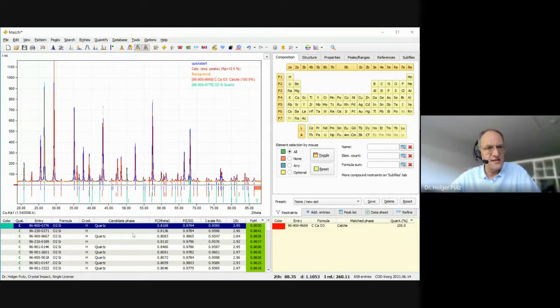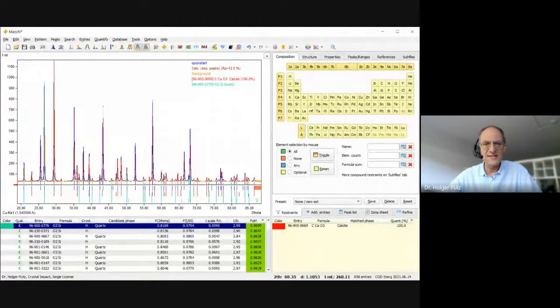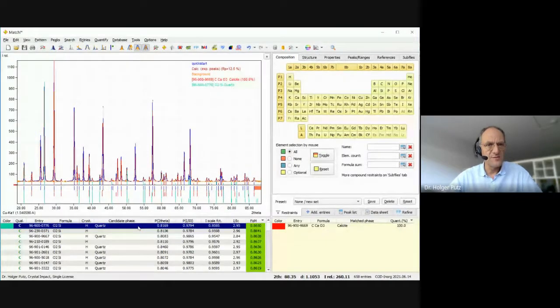And as you can see now in the candidate list, there is no more calcite given here because the peak intensities are no longer present. And the next best matching phase here is quartz. And I can also select it as matching, because it looks very reasonable here in the diffraction pattern. There's a good agreement to the experimental diffraction pattern given in blue.